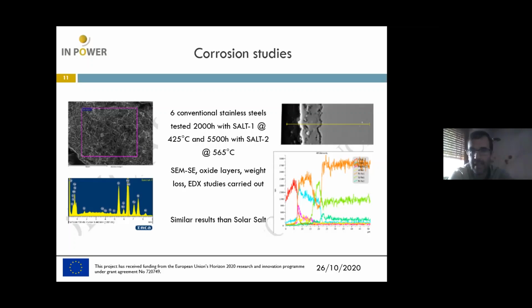For example, AISI 304, 316, 316 with titanium, 321, and so on. And we also developed SEM-SE studies, oxide layer behavior, we determined weight loss, and EDX studies, all well carried out. And the results, for those temperatures that are, let's say, the more aggressive conditions for the two salts, were similar to those obtained for solar salt. So we expect the same corrosion behavior in any conventional steel as for solar salt. So one of the problems was avoided. We can use these compositions without problem in conventional stainless steels.